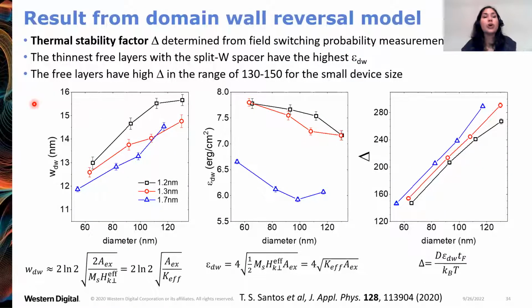Okay. So what we wanted to know from the study is this trade-off between the thermal stability factor and the switching current density. Here, the thermal stability factor delta, we found from field switching probability measurements, and we fit the results to a domain wall reversal model, because with this size of devices, we know that we're in the domain wall reversal regime. This analysis gives us domain wall width, domain wall energy density, and the thermal stability factor, which is found by taking the domain wall energy density multiplied by diameter and film thickness over kBT. And what we find is that it's these thinner free layers with the better magnetic properties that have a domain wall energy density that's a lot higher, and this brings us a high thermal stability factor, even though the layers are very thin.